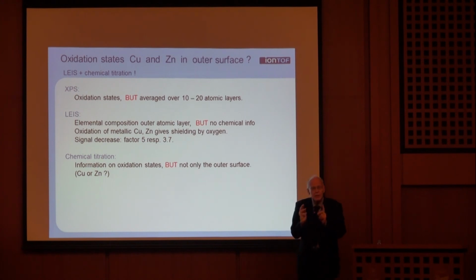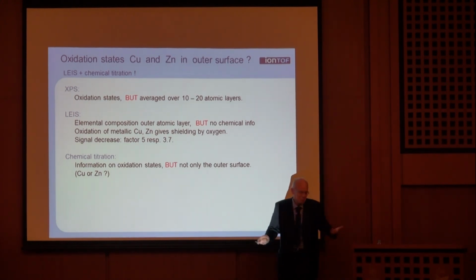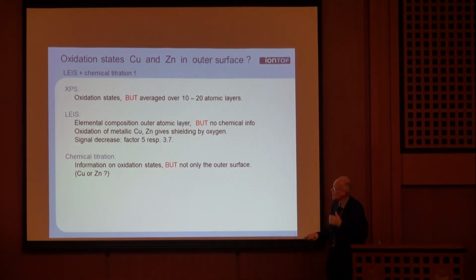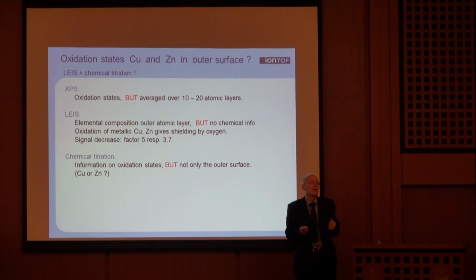When you do XPS, you get the oxidation state with very high accuracy, but averaged over many atomic layers. And what you would actually like to know for a catalyst is the oxidation states in the top atomic layer. Now, in ion scattering, we just get atoms only. So, what do we do? Well, there is a third technique, which is a very complicated one to do accurately: chemical titration. You expose the surface to something like N2O, and you see how many oxygen atoms you can use to oxidize. Of course, you may oxidize the top layer, but also the second and the third layer, and you oxidize the copper and the zinc, and it's not so trivial.